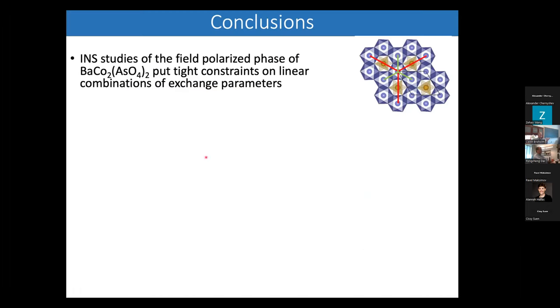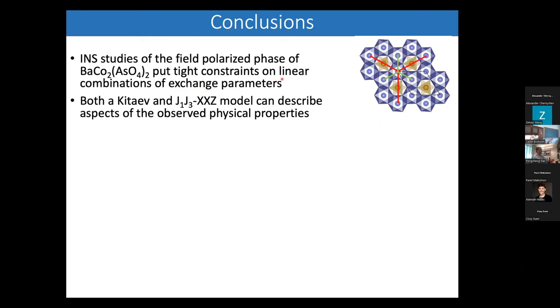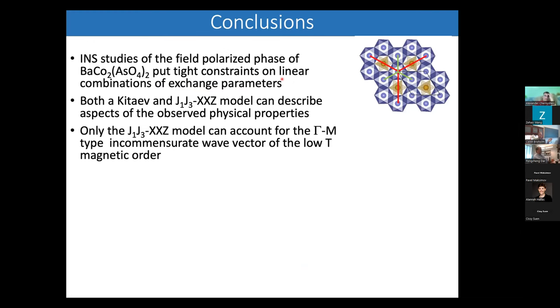We've done an inelastic scattering study of the honeycomb anisotropic antiferromagnetic material. Both the Kitaev and the J1, J3 model can describe some aspects of the observed physical properties. However, only the J1, J3 easy plane model can account for the incommensurate phase with this gamma to M wave vector. And it's also the only model that can actually account for the coherent modes that we observe in the presence of an applied in-plane magnetic field.